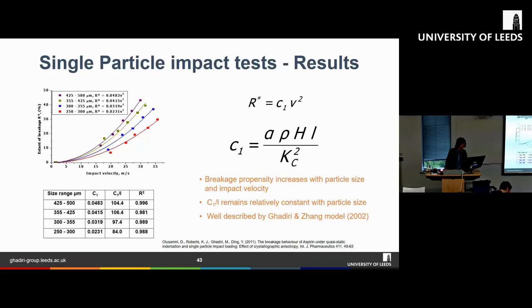And then the conclusion we can see here, what this plot is telling us is that bigger particles have a higher tendency to break compared to smaller particles. So you can see here different size ranges, and then here are some of the parameters that we get as a result of this type of analysis. You can see that breakage propensity increases with size and impact velocity, as I mentioned, and then C1 over L, which is like this,